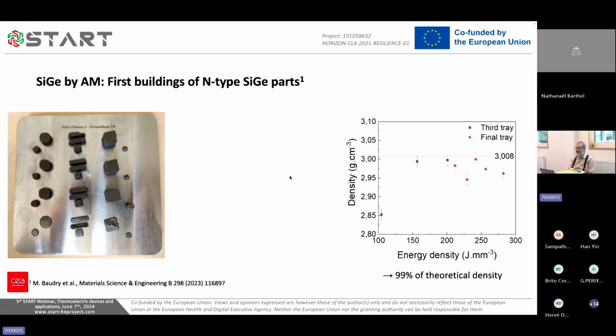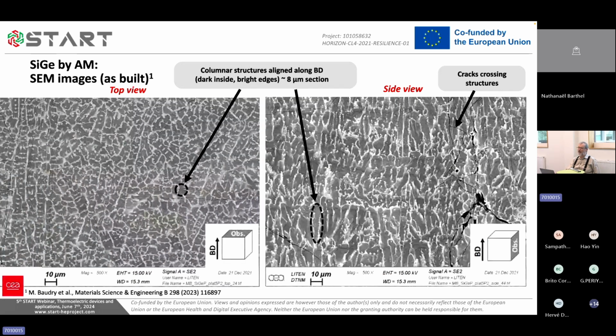So this is on the left our first building plate, so it does print. That's the good news. We do get good density, close to theoretical. Of course, there is some bad news. So you see here some pictures. The top view from above in the building plate, and a cut in the building direction. So it is a typical columnar growth for AM. This is very common here. You see that we get some cracks here.